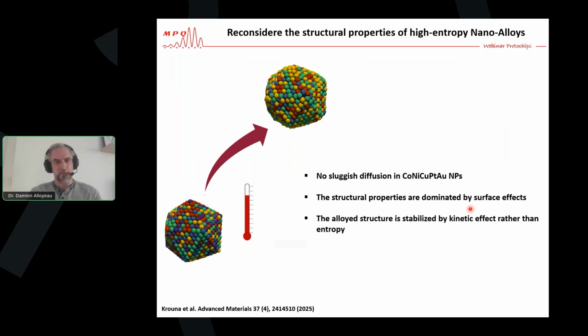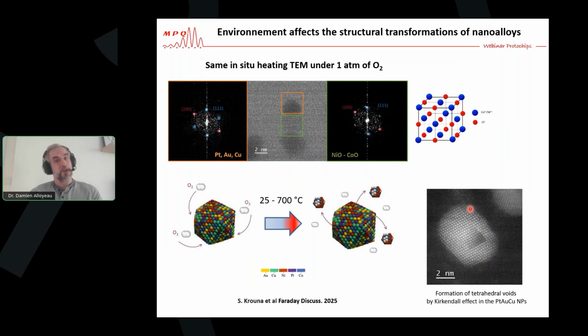But pay attention, another very important take home message: the environment is also extremely important. So if you work in synthesis conditions that are oxidizing, you should follow this recent publication that we did, exactly the same in-situ heating experiment, but this time under 1 atmosphere of oxygen using the gas cell system from Protochips. And this time, when you work in an oxidizing environment, it's not the gold and the copper that go to the surface. You have a segregation of nickel and cobalt, which are the two metals that have a strong oxidizing behavior.